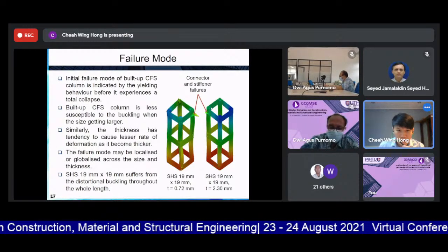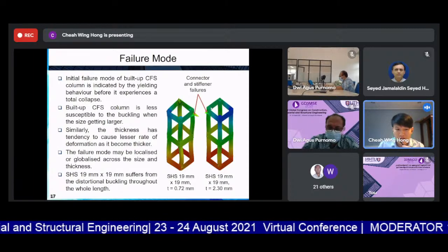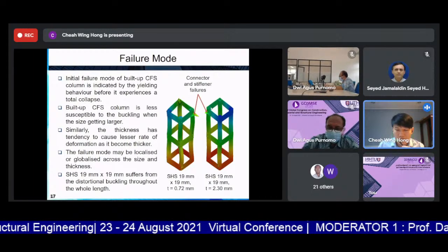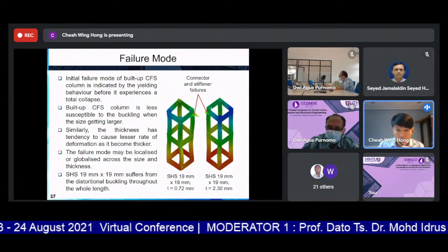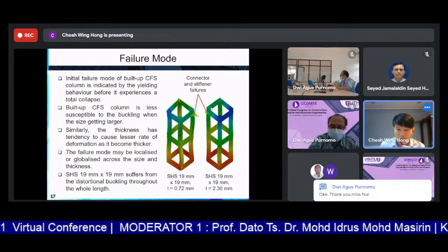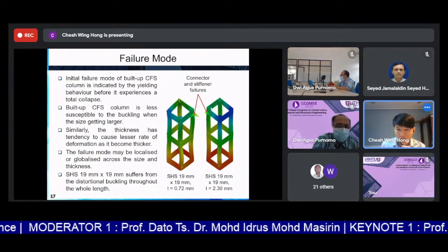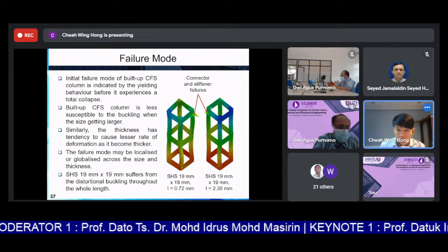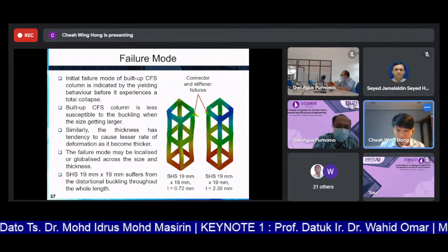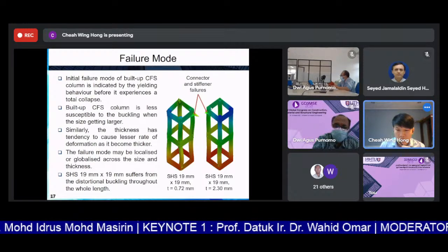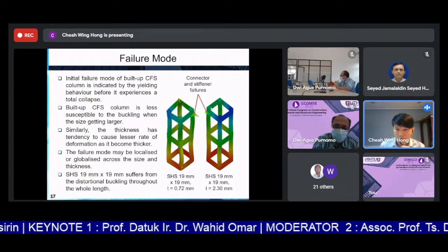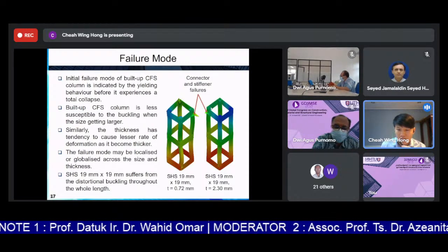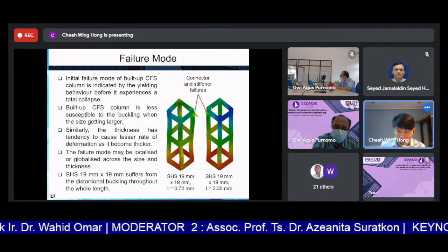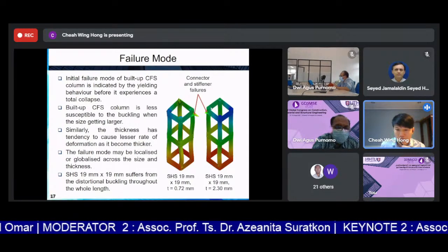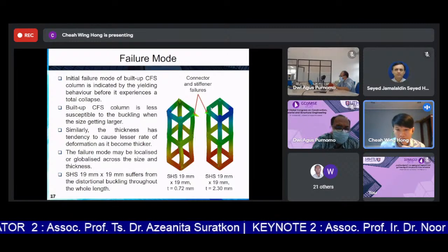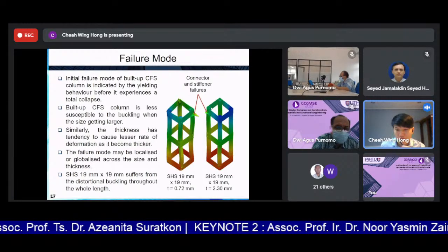And the failure mode may be localized or globalized across the size and thickness. So the SHS of the smallest size, 19 mm times 19 mm, suffers from distortional buckling throughout the whole length of the SHS. And this figure shows the SHS with a size of 19 mm times 19 mm, with a thickness of 0.72 mm and the largest thickness of 2.3 mm. As we can see, the thickness at 0.72 mm shows greater distortional buckling compared with the thickness of 2.3 mm.